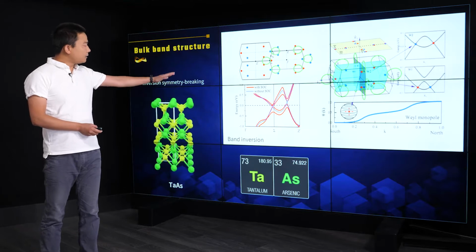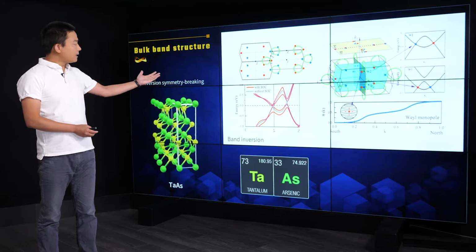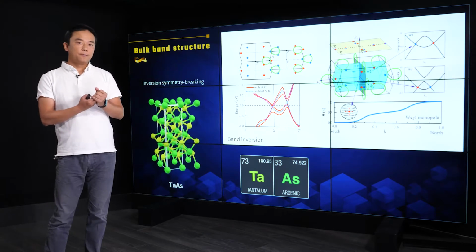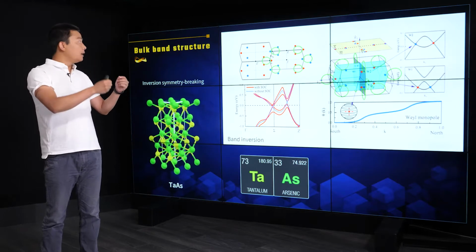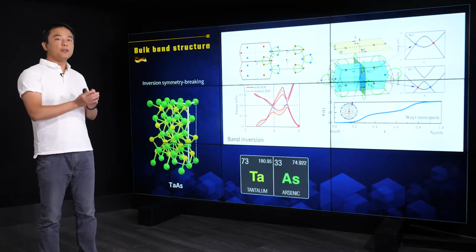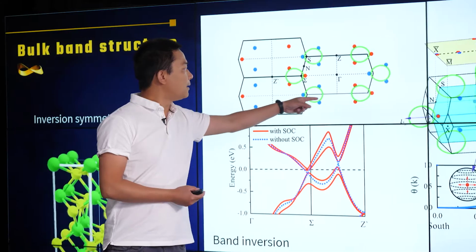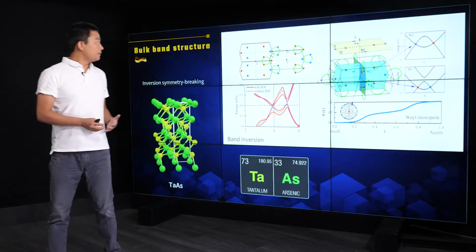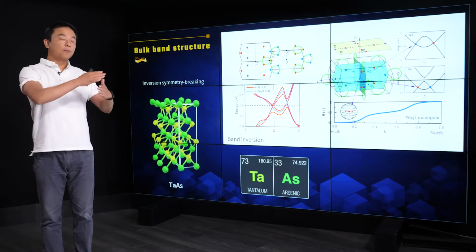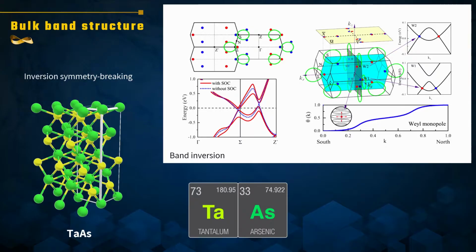Here, the dotted line you see is without spin-orbit coupling. You see the valence and the conduction band cross each other. This crossing is actually not only on these two points, and this crossing will form a ring in this three-dimensional space. Like here, this gapless point forms a ring, these green rings. There are many rings because this material has several mirror planes. And in each mirror plane, there are 3 rings, and therefore in total, there are 6 rings.